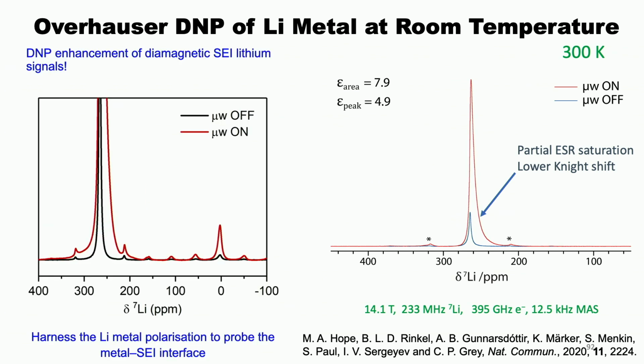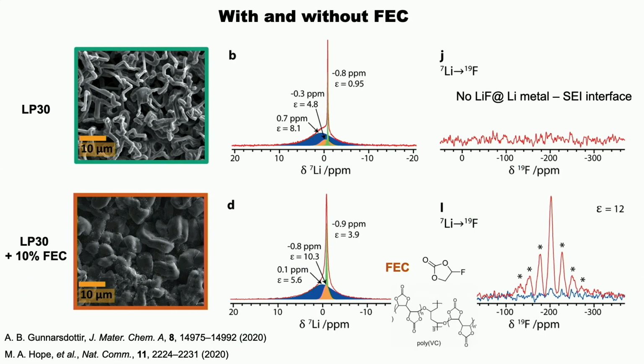But the most interesting thing was we could also polarize the signal of the SEI, so the covering of that lithium metal. And so then the question is, what can we do with this? The first question we had was one associated with what is in this SEI. Bette Gallant's group is a particular pioneer in this area, and has spent a lot of time trying to work out what's in it. They quantify different parts, and you can do XPS, and you can go down to deeper levels. But what's really difficult is to look at that interface between the lithium metal and the SEI. But we can do this directly.